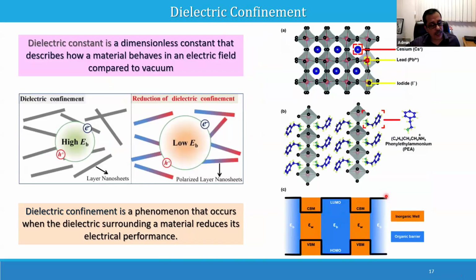So when we analyzed this material, the electronic properties are inferior compared to the lead-based material. Lead-based materials are highly superior when you consider the electronic application for solar cells or light-emitting diodes. So we tried to understand what the problem is here. Basically, in this low-dimensional material, what is the problem? Actually, I showed in the beginning, the charge carriers or the exciton, the electron and hole, are very close to each other, because that is basically within the octahedral unit.